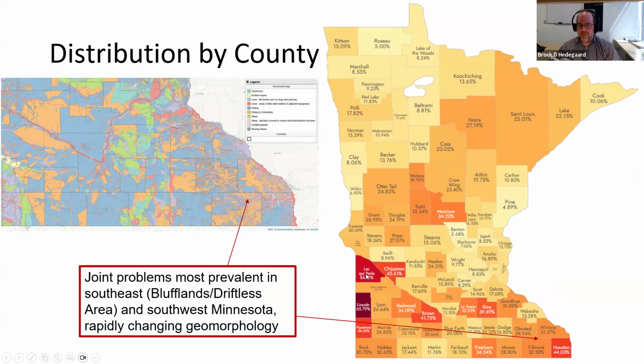One thing that a lot of these locations have in common is that they have rapidly changing geomorphology. So the driftless region in particular in the southeast corner of the state, there's no glacial scour or glacial drift that went through that region. So it has a very sort of hilly and erosion based geomorphology. So we found that in general, locations with that kind of geomorphology had considerably more joint separation, which lends credence to an idea that it is a strongly soil dependent type of motion here. So if you have soil that is not very erosion resistant, for example, then it's much more likely that you may have joint separations.